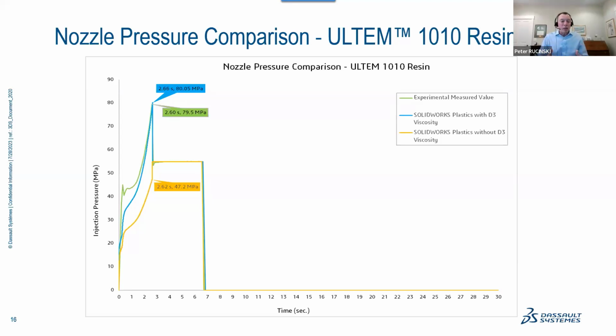We did a little bit of work to our solver. Let's say we turned the D3 coefficient back on. We had to do some work and some tuning to get it just right. And when we finally finished, the result we got was the blue curve. So what you're seeing there is the green curve, the experimental measured value; the orange curve, which is the SOLIDWORKS Plastics solver without taking into account the D3 pressure-dependent viscosity; and the blue curve, which is the SOLIDWORKS Plastics solver with D3 pressure-dependent viscosity taken into account.